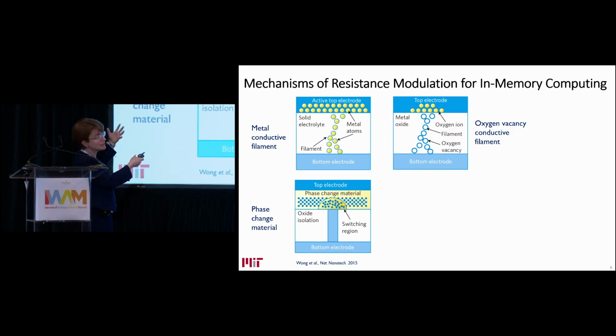Now you electromigrate or extract oxygen out of an insulating metal oxide. And when you are dealing with oxygen, which is very slow at room temperature, you also form dendritic structures for the diffusion path and leave behind electronically conducting zones or electron-rich zones that can also give you modulatable conductance depending on the structure of these dendrites. So these are rather simple structures, two-terminal, but the formation of these filaments is highly uncontrollable, very difficult to control in practical structures, and compromises the reliability in the training of these devices.